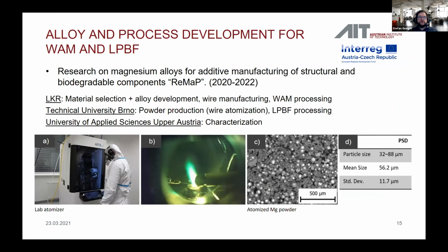Yeah, another project I want to show you is the so-called REMAP project, where the focus is on materials development and additive manufacturing processes. So both the powder processes using laser powder bed fusion and also, again, the wire arc additive manufacturing. We use both processes for comparison, and we produce the powders and the wires in-house in order to establish the whole processing route for investigations within the project team. In this picture, you can see the lab atomizer used at the partner, the Technical University in Brünn, and the first batch of magnesium powder with a particle size ranging from 32 to 88 microns and a mean size of 56 microns.